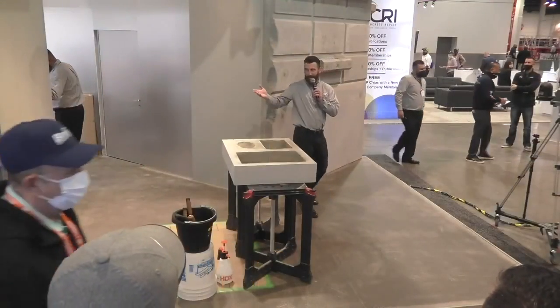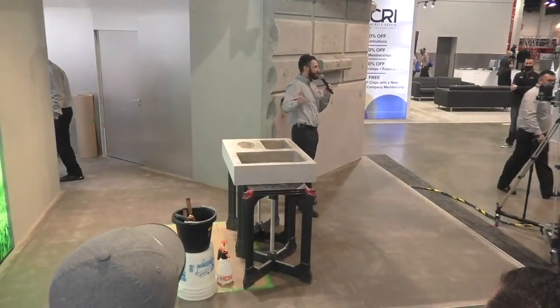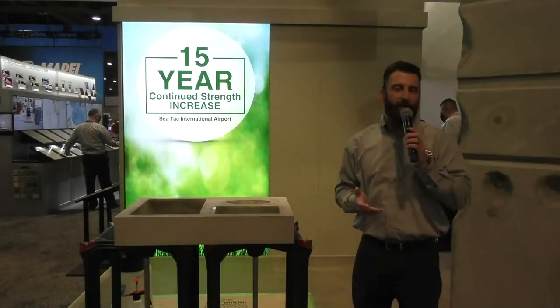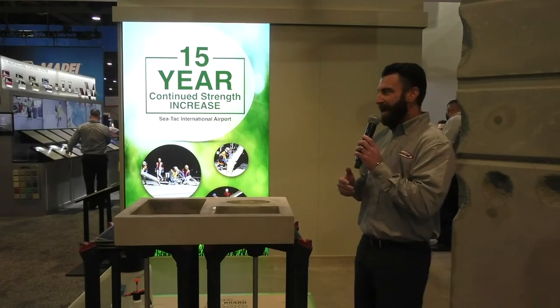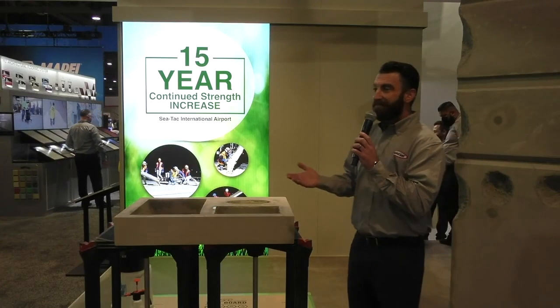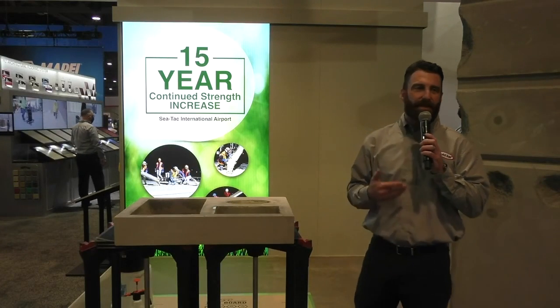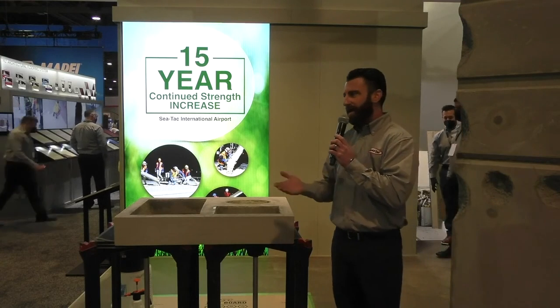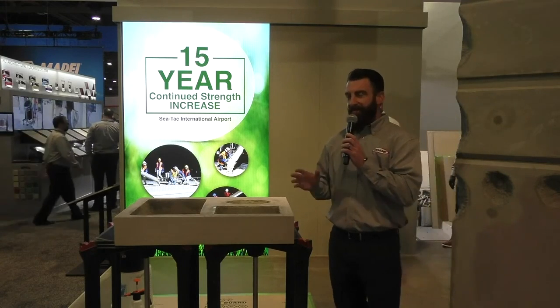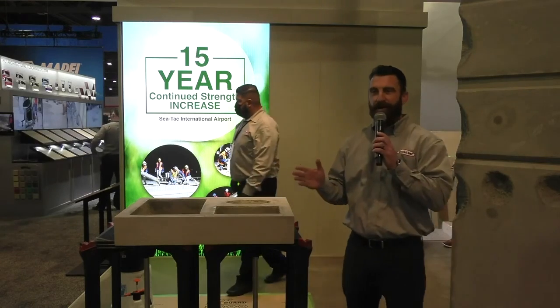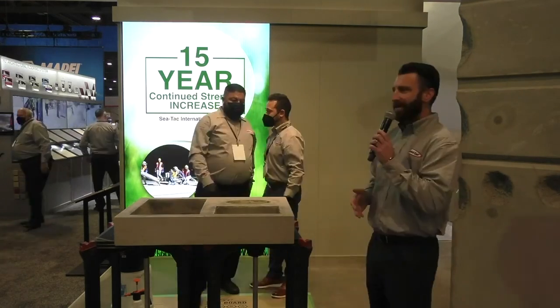Now, I mentioned it's got long-term durability. We actually placed Rapid Set concrete at SeaTac Airport back in the mid-90s, and we had an independent lab come out and test it 15 years later, and they determined that the strength continued to increase well beyond the 28-day mark. In fact, the flexural strength of that airport is now at least double what it was in the mid-90s.